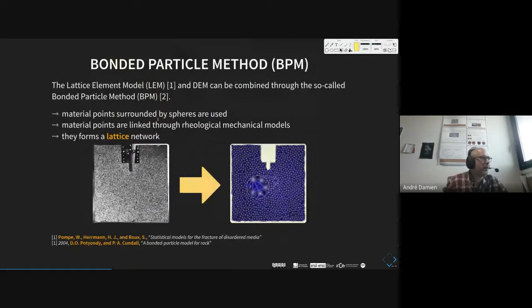So the idea is quite simple. In fact, it comes from the lattice element model, which is named LEM, which is quite an old idea. And we can combine LEM and DEM through the so-called bonded particle method. The idea is quite simple. We have material points which are surrounded by spheres. In fact, these are the discrete elements, which are mainly spherical, but we can use other geometries. We will see that after. And these material points are linked through a very simple rheological mechanical model. And all these material points form a lattice network, as you can see in this picture.